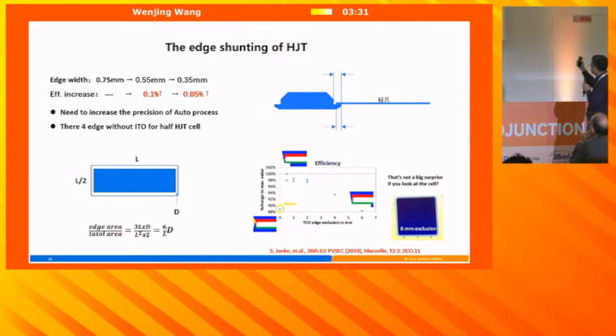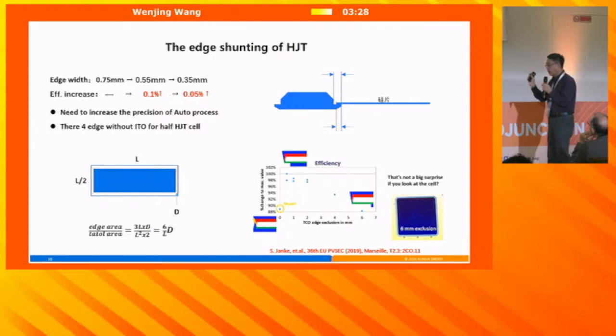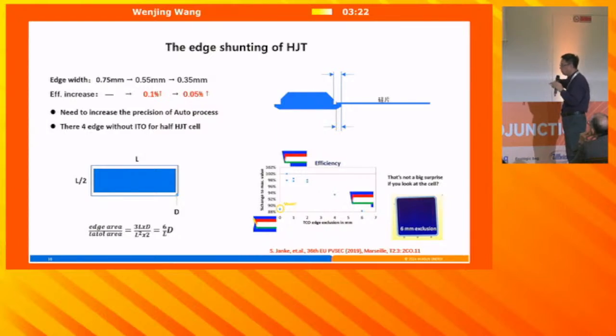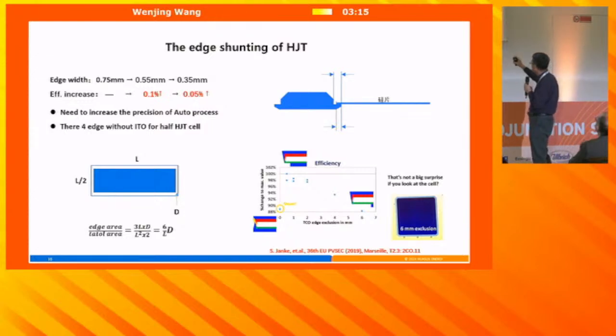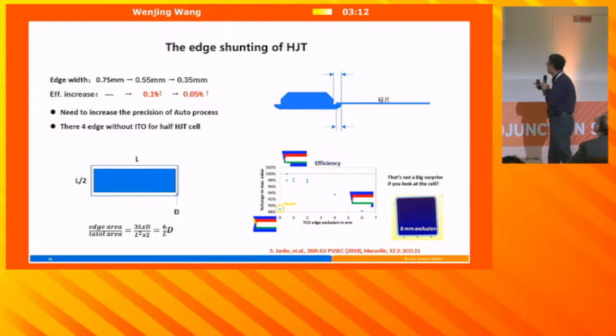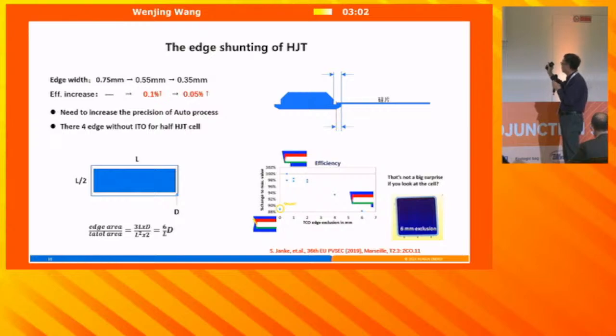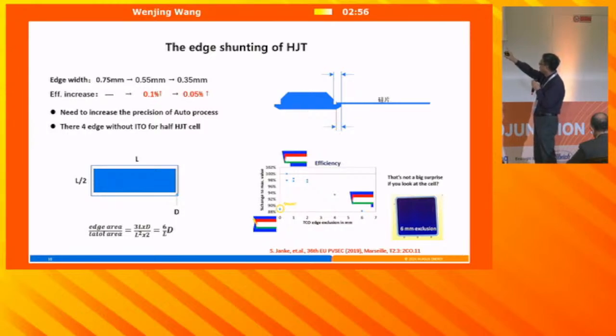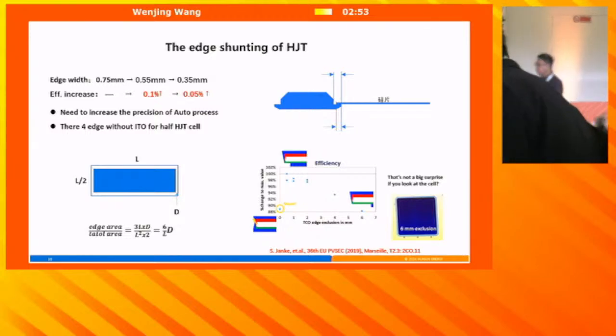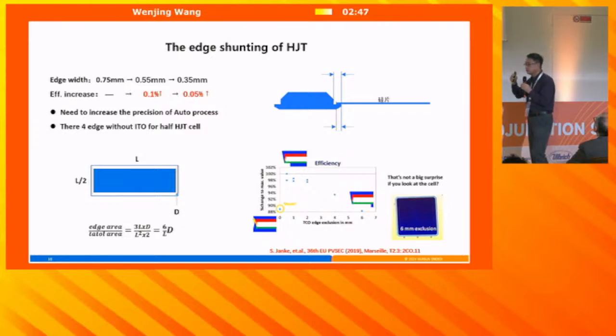And also for the edge of the backside, there is no ITO. If the ITO covers the whole back surface, there is some shunting, some leakage between front and backside, so the fill factor will be degraded. But if this no-ITO area is too wide, it will also decrease the fill factor. So we reduced the edge width from the very beginning of 0.75 millimeter to 0.55 millimeter, and that increased efficiency by 0.1%.